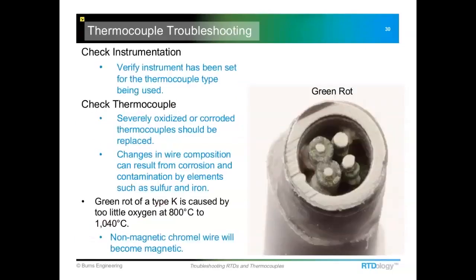So this is an example of corrosion that can happen in a type K thermocouple. You can see all this green stuff, and it's selective oxidation of the chromel wire inside the probe. It's caused by a lack of oxygen in there, and it will corrode it. Some ways to get around that would be to switch to a different type, like maybe a type N. You can also increase the available oxygen level, which could help. And the other thing that you're probably better off doing is just to replace it on a more frequent basis so you can avoid this kind of thing.